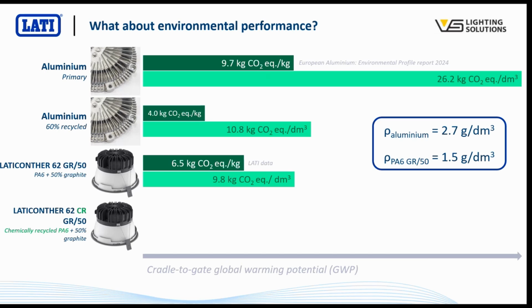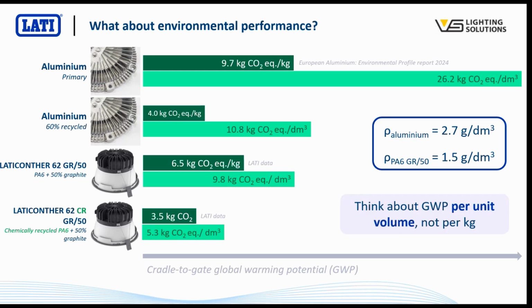We use that to make this version of the same thermally conductive plastic, exactly the same mechanical performance as the virgin grade, exactly the same thermal conductivity. But the GWP is around half of the virgin material, and again we're now comfortably less than half of the aluminium, even accounting for the fact that we use recycled aluminium. So the important point to note here is if we're comparing environmental performance, let's not look at GWP per kilo, let's look at it per unit volume.